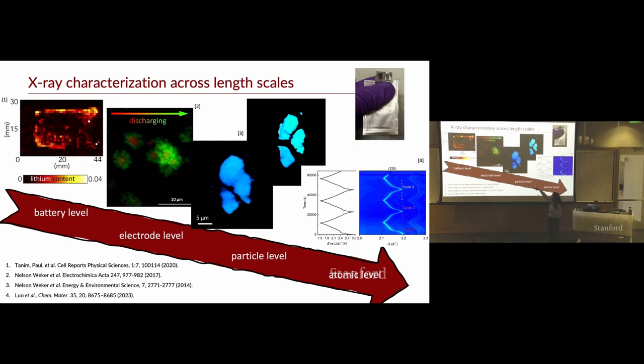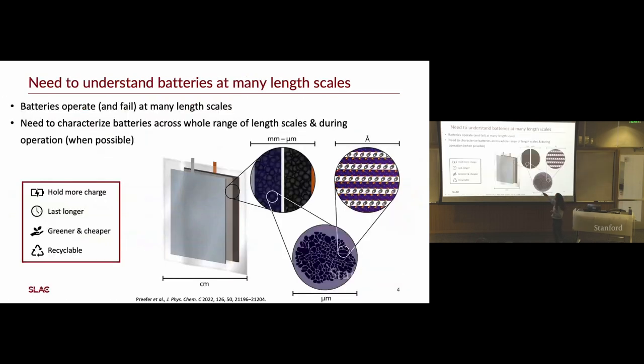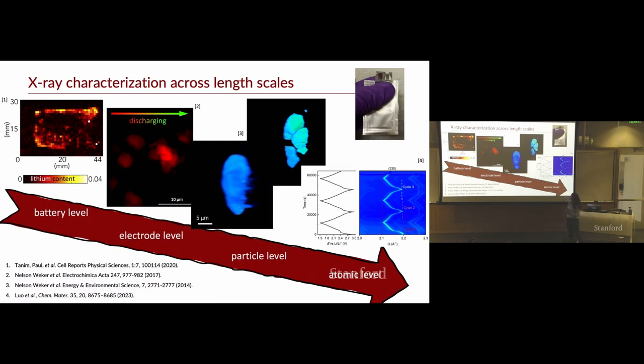The next slide here, which is the green and red picture, combines chemistry and microscopy. And it's looking at multiple particles on a cathode and how when you're lithiating them, they are both breaking apart, so going from a micron-sized particle to nano-sized particles, and also having a chemical reaction because lithium is going into the particles. And so we can actually look indirectly at where the lithium's going because of the chemistry changes. Those two images back there, I can start it again, are movies. That's of anode particles, looking at a single particle in the lithiated state and a delithiated state in 3D. And you can see that when you have 3D information, you can see cracks forming in particles.